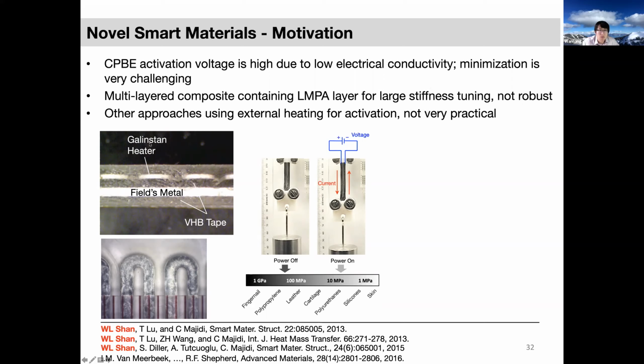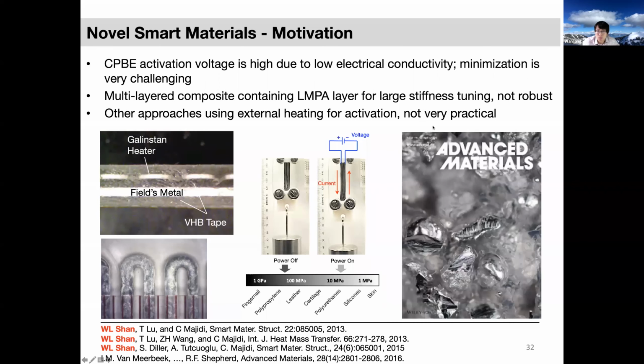There are also other approaches using external heating for activation, which are not practical. For example, this one was done by the Robert Shepherd group at Cornell. They made an elastomer foam first, and then tried to infiltrate LMPA into the pores of the elastomer foam. They claim it to be a bi-continuous foam, but from the results they showed, we would argue that the particles are not that well connected, and they have to use internal heating for activation. So this all motivated us to engineer and design better smart materials to fit the needs of all sorts of soft robotic applications.